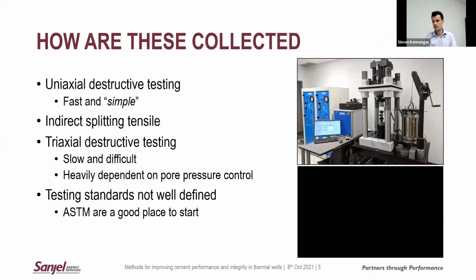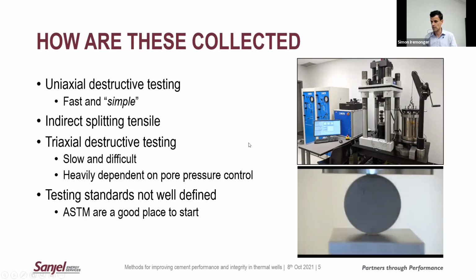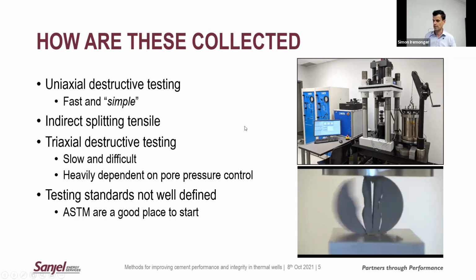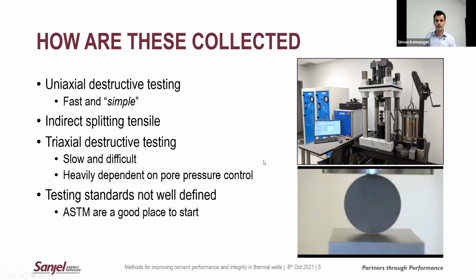So how is this collected? How's this testing done? Typically you're using triaxial load frames. You can normally just do it under a uniaxial load. So that's where you're just simply applying direct axial load and crushing a sample. This is relatively fast and simple if you have a load frame. You can do an indirect splitting tensile test here. This is known as the Brazilian method. So essentially, while this looks a little bit funny in that you're still crushing a sample and not necessarily pulling it apart, the way that you are actually applying load within that is under tension. And so you can quite readily get tensile strengths without having to do the complexity of pulling on something.